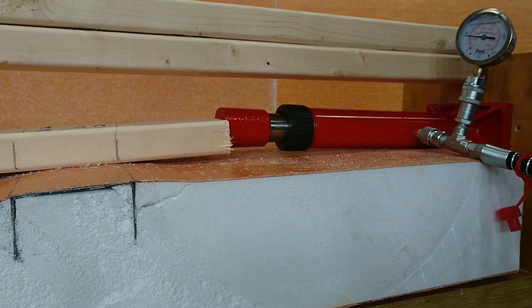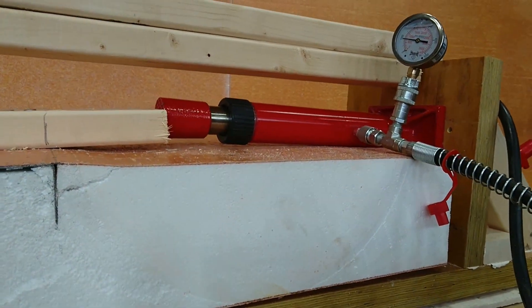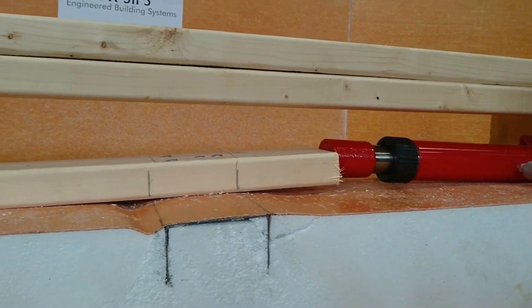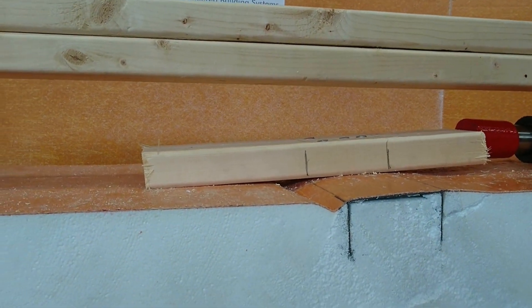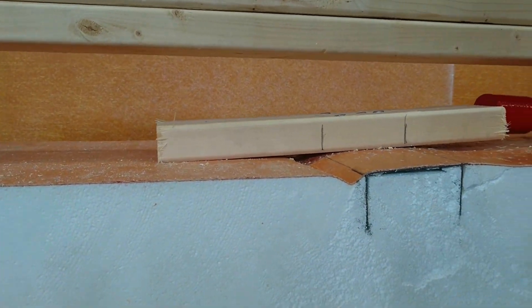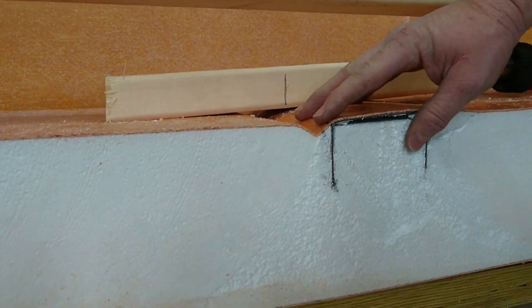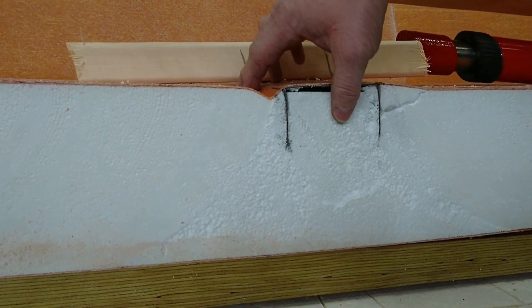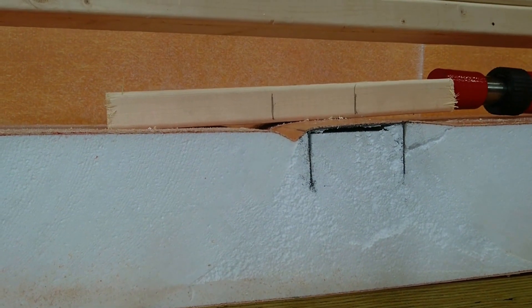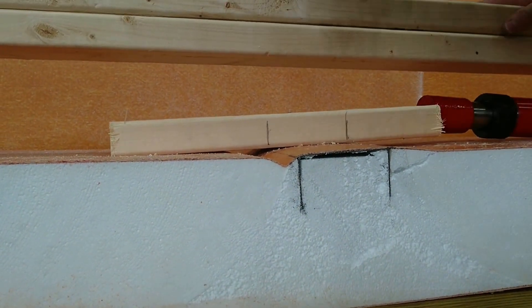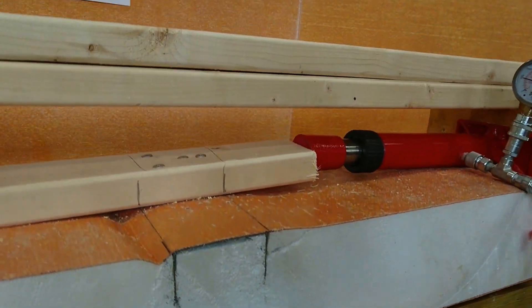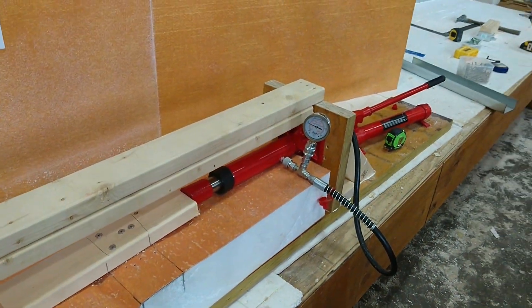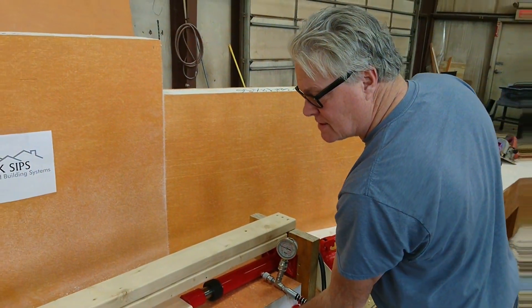And right now we're on, pretty impressive that we're over 1,000 pounds just with that one piece of 2x4. I'm going to go ahead and put it again and see if we can do anything else. You can still see that buckling failure very, very pronounced now where we're pulling this right in with putting that under such tremendous amount of compression and tension. The fiberglass is at compression right here. It's in tension on this side. Absolutely can't fail on the bottom. It's going to fail there with a buckling failure, which is a very common. If we test this panel for flexural strength by putting weight straight down on here, we'll get a buckling failure on the top also we wouldn't get one on the bottom. And you can see we're actually ripping apart and crushing the core on that. So that's a very good indication of the pretty amazing strength of our panel system here.